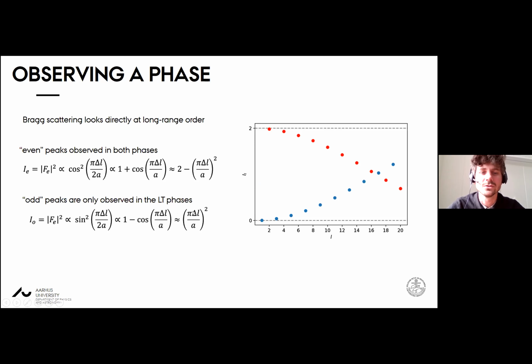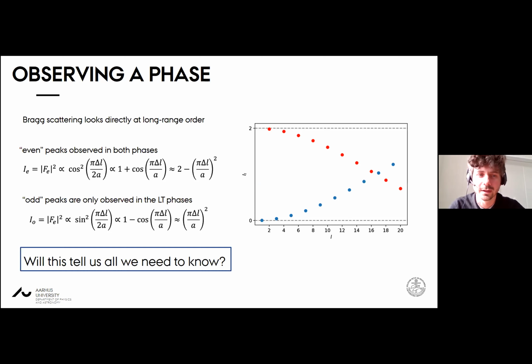Okay, so as you increase your lattice distortion, you'll see a series of peaks growing with increasing intensity, with a series of peaks that are decreasing in intensity. Okay, and the usual process is to pick one of these Bragg peaks, say this one, and pump it and watch it and hopefully see it go to zero. And that will tell you about the phase transition. Okay, so the main goal of my talk is to answer this question. Is monitoring these Bragg peaks, which has been done for quite a long time now, telling us everything that we need to know about the dynamics of the system?